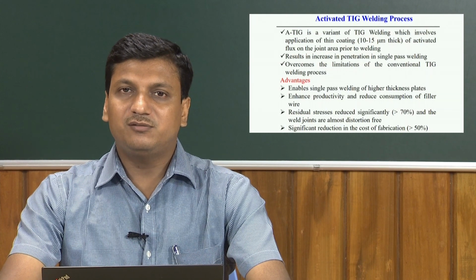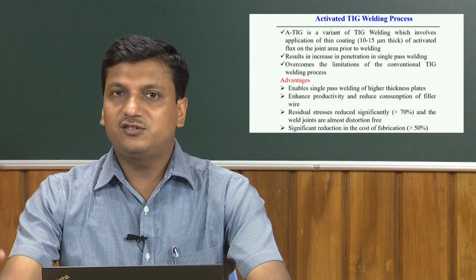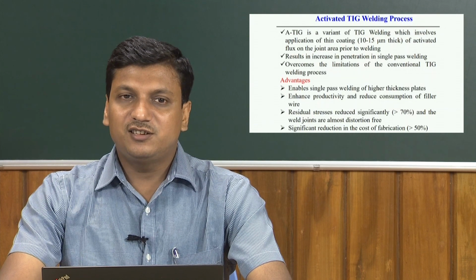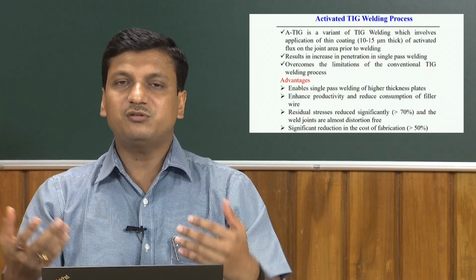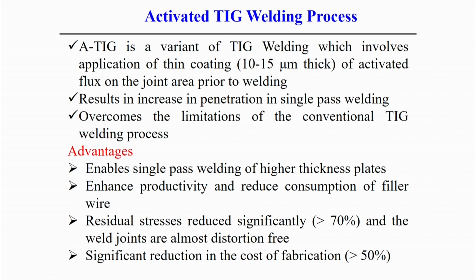Once we do the normal welding process, the surface active elements actually affect the weld pool, and it finally changes the weld pool shape and size, impacting the final weld joint properties. In this way, the A-TIG process is the way we can overcome the limitations of the conventional TIG welding process. Of course, A-TIG, the activated TIG welding process, simply uses the coating, but some researchers have also developed directly adding the surface active elements, for example, carbon dioxide with the argon shielding gas, and that can also be used as a modified TIG welding process to include the effect of the surface active elements. But in the activated TIG welding process, normally we use the coating of the activated flux. So, that is the difference here.